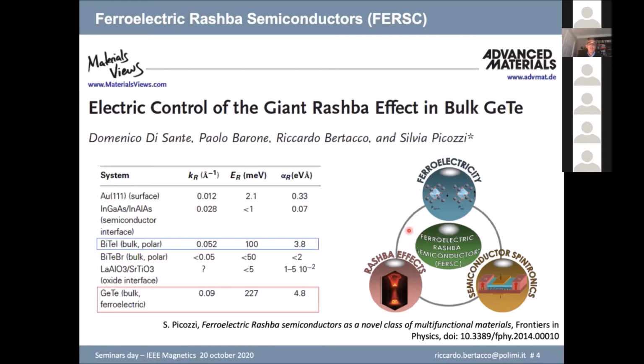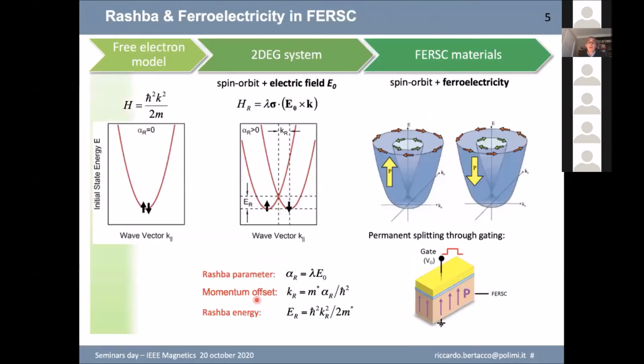Now, the interesting story is that the entity of the effect, especially the Rashba effect, which is a spin splitting of the bands, is not negligible at all. It's really large, with an energy splitting of 220 millielectron volts, which means you can work at room temperature. And this is really the key advantage of this class of materials. So let's start from Rashba, and everybody knows the case of the electron parabola. Now what happens if you have a two-dimensional electron gas in which you switch on an electric field? You typically have this splitting of the bands. And in these bands, the key parameter is this energy separation, which is E_R. As I told you, in germanium telluride, it will be on the order of 230 millielectron volts, sorry.